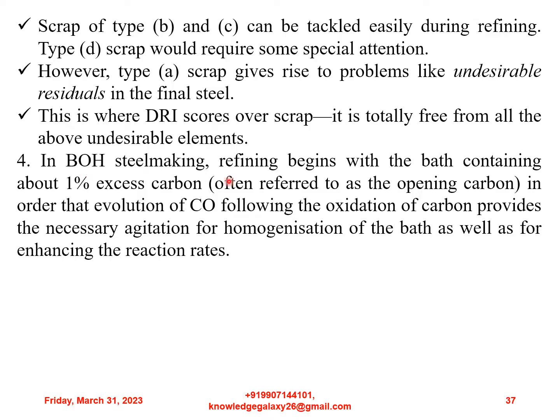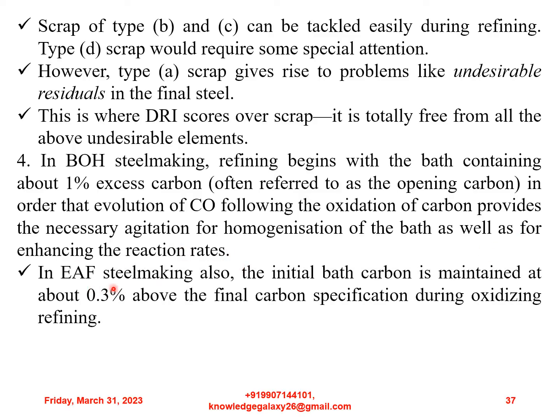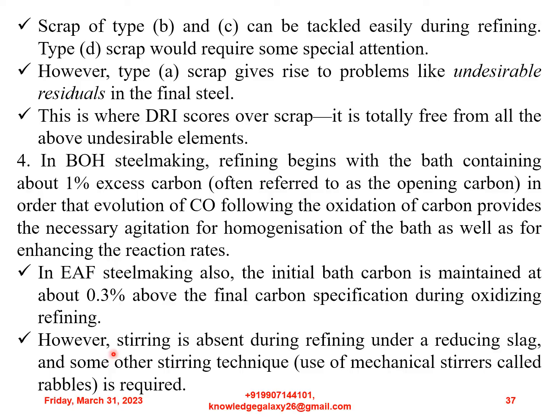In basic open hearth steel making, refining begins with the bath containing about 1% excess carbon, often referred to as the opening carbon, in order that evolution of CO following the oxidation of carbon provides the necessary agitation for homogenization of the bath as well as for enhancing the reaction rates. In electric arc furnace steel making also, the initial bath carbon is maintained at about 0.3% above the final carbon specification during oxidizing refining. However, stirring is absent during refining under a reducing slag, and some other stirring technique, use of mechanical stirrers called rabbles, is required.